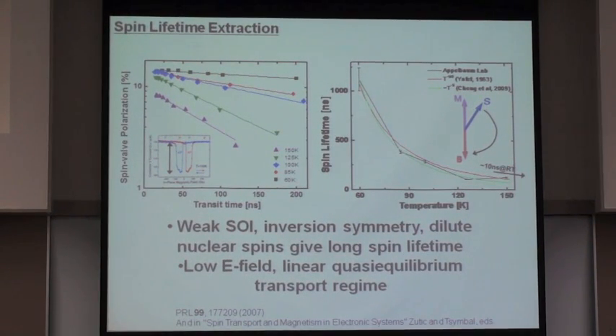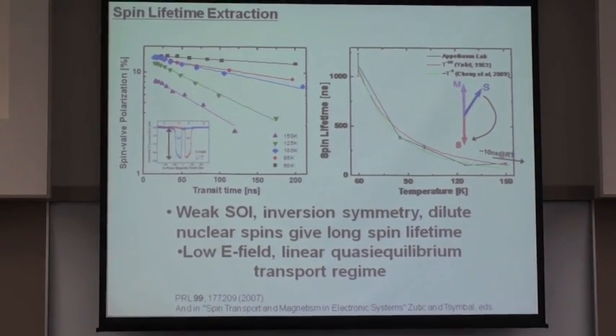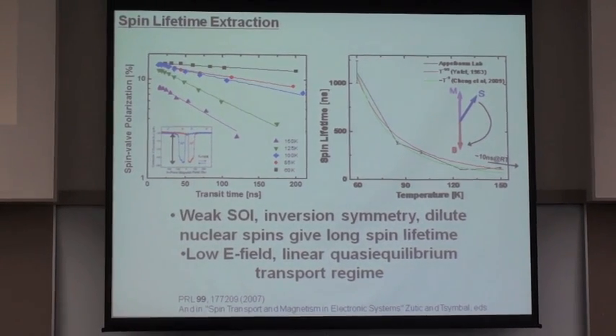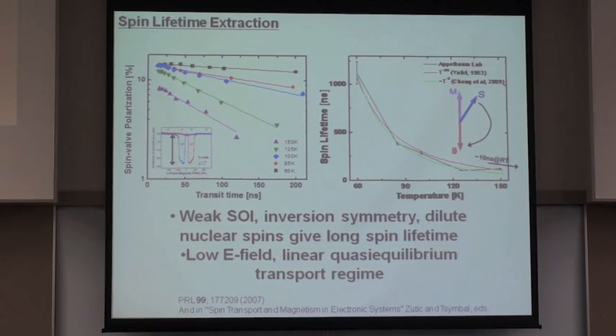And of course, we can see the effects of changing the temperature due to the fact that the spin lifetime, although it's very long, is of course finite, and it's limited by the residual spin-orbit interaction, which results in spin flips through electron-phonon scattering. Now, I want to point out here that these kinds of measurements were done in relatively small electric fields, where the system was more or less in equilibrium.